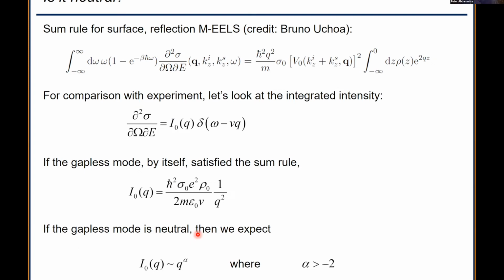So as I mentioned earlier, a conventional plasmon satisfies the F-sum rule. The F-sum rule in 3 dimensions says the integral of chi double prime over all frequencies is proportional to the number of electrons times q squared. So if it's a demon, then it should not do that. It should actually go faster than that because the excitation is neutral. It doesn't screen in the limit of low momentum, so it has to violate the F-sum rule.